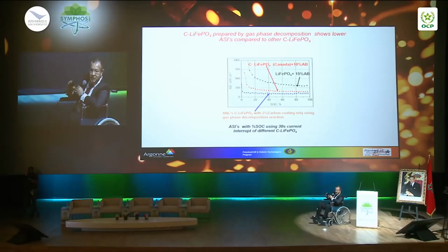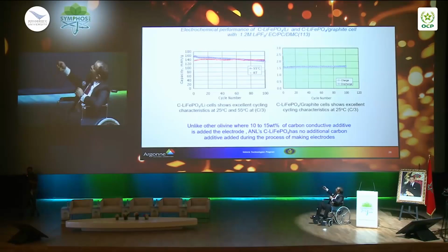Because gas-solid reaction is the best way to create a good protection and good surface coating. And performance-wise, the material performs very well at high temperature and room temperature, and this is in a full cell. We have data that shows thousands of cycles. I couldn't find it because it's a little old. But the bottom line is, when you do a nice carbon coating, you can get very high rate capability with this material.